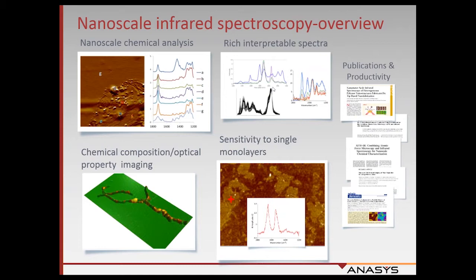These spectra are highly analogous to FTIR, conventional infrared spectroscopy, and so you can apply the same type of interpretation that you would to conventional infrared spectra. We can also tune our laser source to any individual absorption peak and then do chemical composition mapping to visualize the distribution of different chemical species in biological and other samples. And the sensitivity of this technique, as I'll show you, can go down to the scale of single monolayers. So it has applications for very small samples, proteins, membranes, things like that.